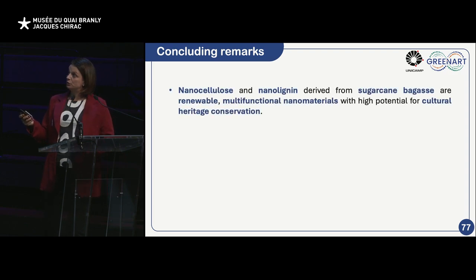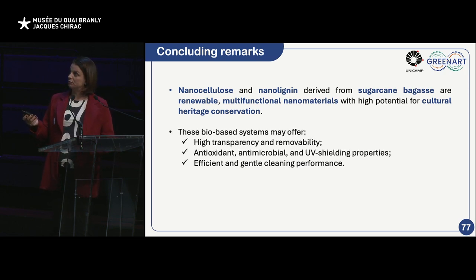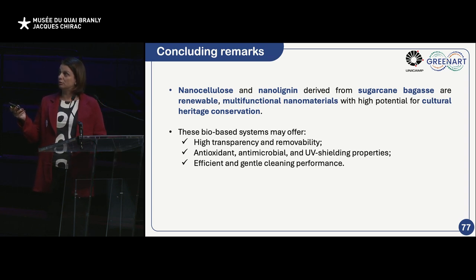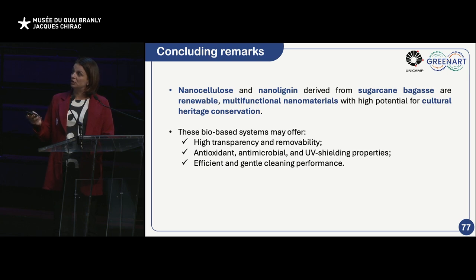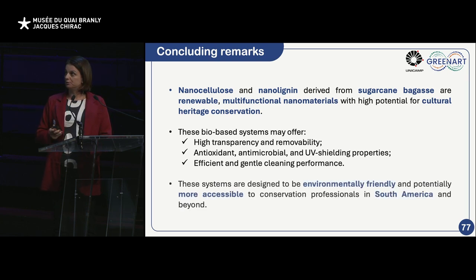So just to conclude, we wanted to show you that these nanocellulose and nanolignin derived from sugarcane bagasse are renewable, multifunctional nanomaterials with high potential for cultural heritage conservation, both for hydrogels and for the protecting films. They are bio-based systems that can offer high transparency and removability, antioxidant, antimicrobial, and UV shielding properties in the case of the films, and also efficient and gentle cleaning performance for the hydrogels.